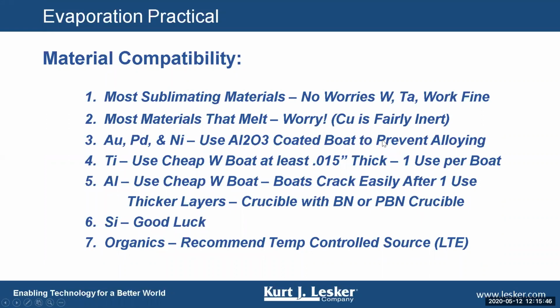When it comes to material compatibility, one considers materials that sublime. Generally, they don't interact with the boat or the crucible that's holding them. And as a rule, they work fine in just about any kind of boat material or crucible material. Most materials that melt do stand a good chance of interacting with the evaporation source, so you have to be cognizant of that. Generally, experience is a good indicator. People usually know what kind of boat material works with a certain given material.